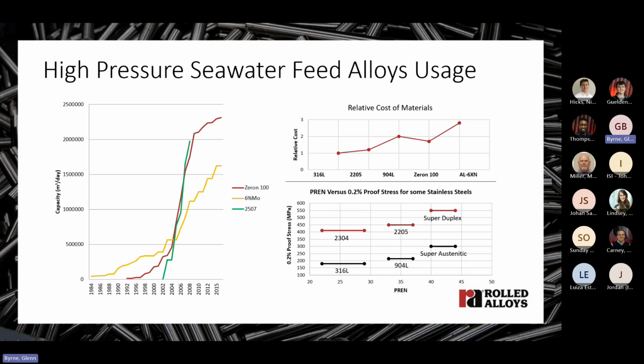This realization also coincided with a technology transition in the industry and a move from MSF and MED to seawater reverse osmosis technology. Seawater reverse osmosis was increasingly more energy efficient, cost effective, and scalable. The new plants were generally bigger than before, 100,000 to 300,000 cubic meters a day, and there were more of them. So the installed RO capacity of both Zeron 100 and 2507 soared over this time period, while the utilization of 6MO tended to lag. And this is primarily because of its lower cost. The super duplex alloys tend to be about 30% lower in cost than the super austenitic stainless steels.